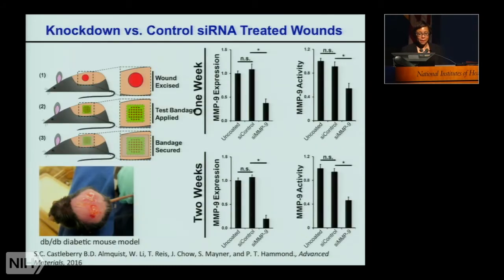So here we're getting very significant loadings of siRNA in this range of 10 to 20 micrograms per centimeter squared. We then used a diabetic mouse model, and we'll have a control wound in which we don't introduce any treatment. We also have a second control in which we're using a scrambled siRNA, which doesn't encode for anything, and we're using our siMMP9 treated system.